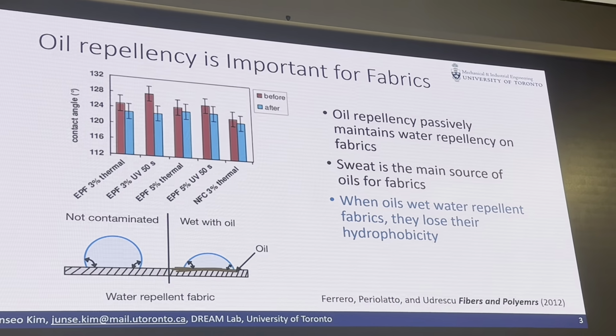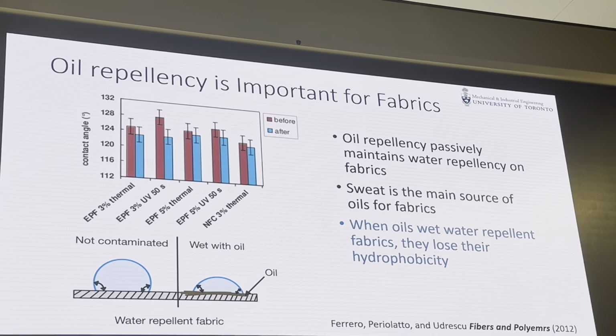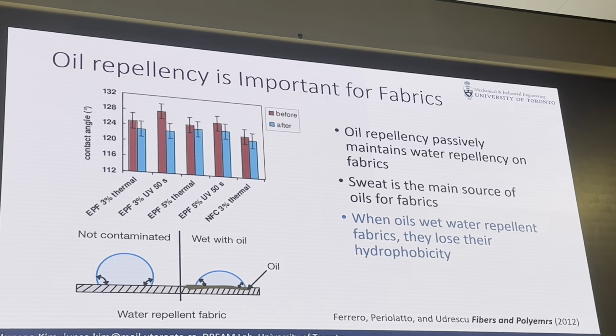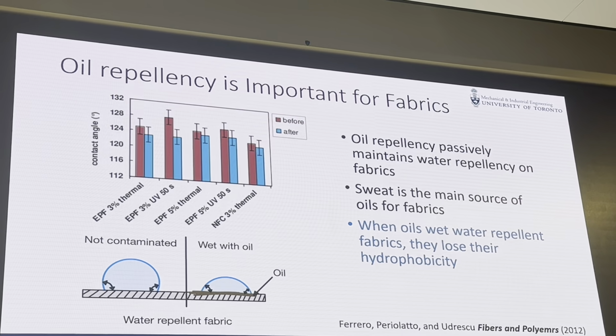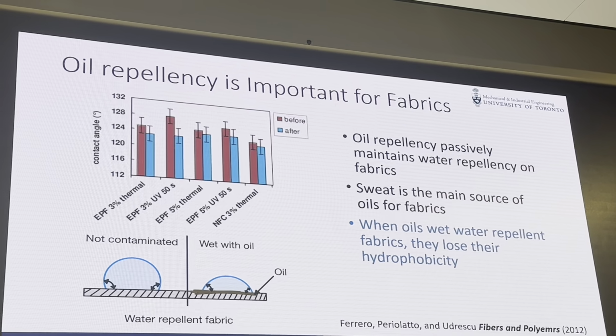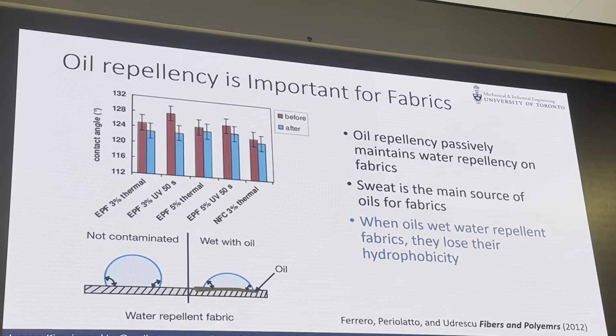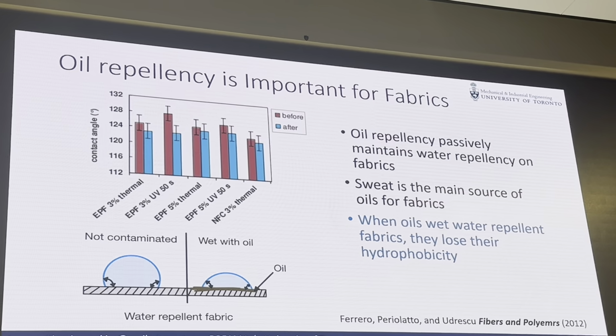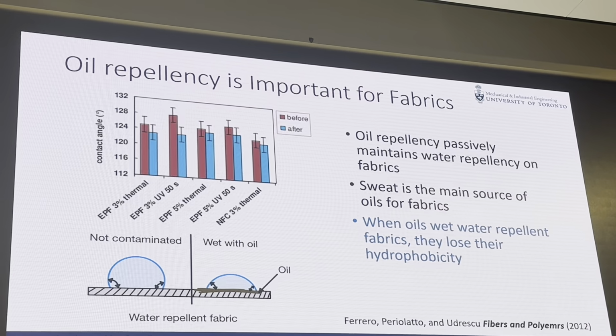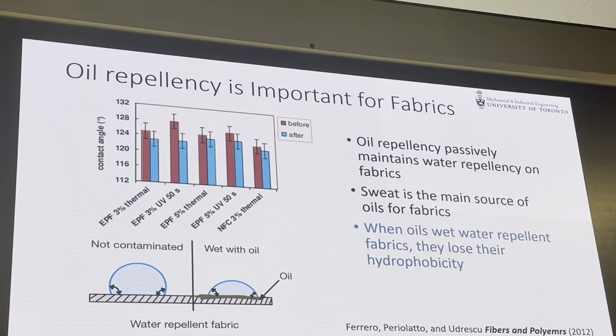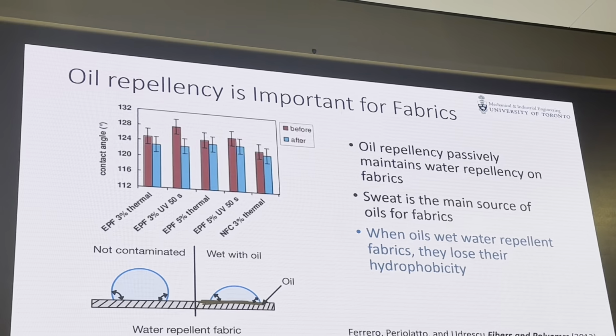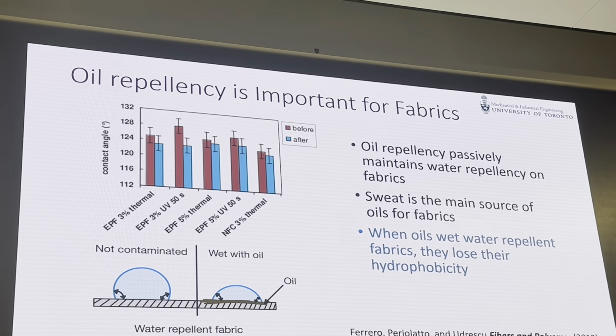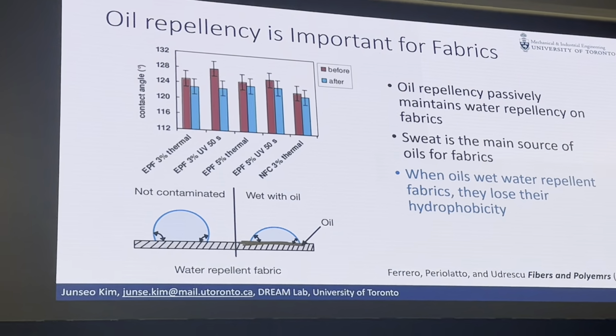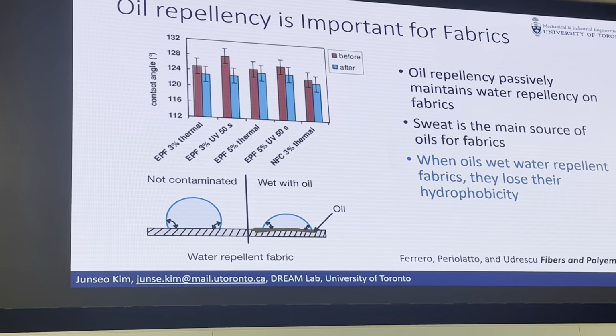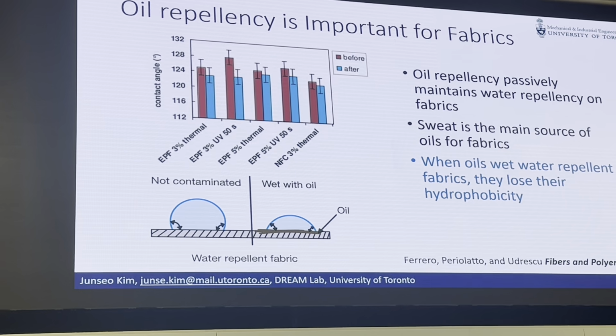So, oil repellency, why is it important? Well, it's important for fabrics. If I direct your attention to the figures on the left, what this proves is that when water repellent coatings or coated fabrics are soaked in oil or wetted by oils, they reduce in their hydrophobicity as well. So you can take a look at the figure. Before and after submerging in oil, the water contact angle, which quantifies the repellency, is reduced. As well as the figure below showing how that's also reduced.